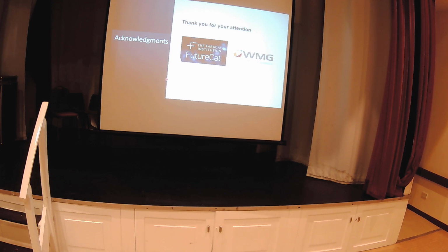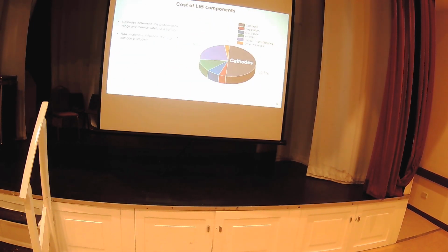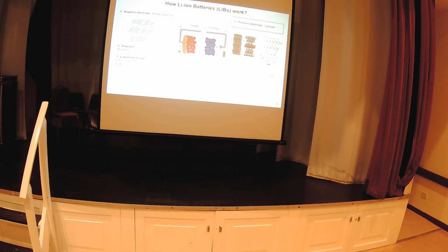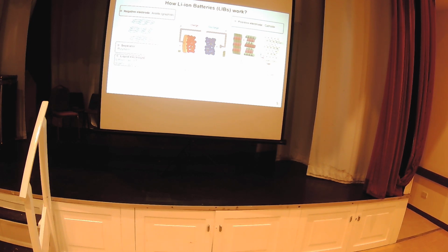So it depends on, for example, if I show you how it looks. They are improving this because all the lithium, when you extract it, comes here and sits on the anode side. The anode is a honeycomb structure. If you can improve the structure, the amount of lithium that can sit there improves. This can lead to fast charging. Thank you very much. So it doesn't matter about the cathode for the charging speed?